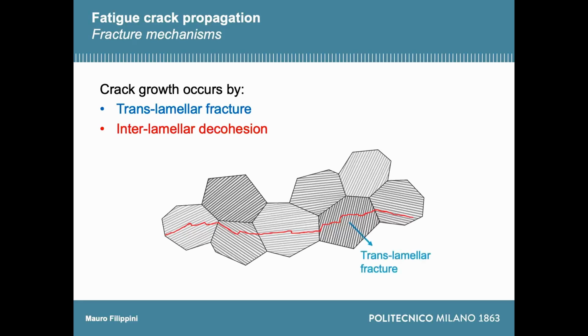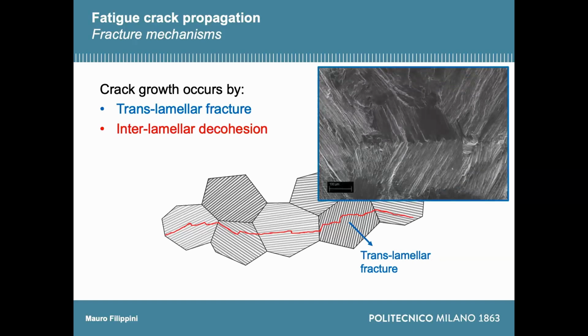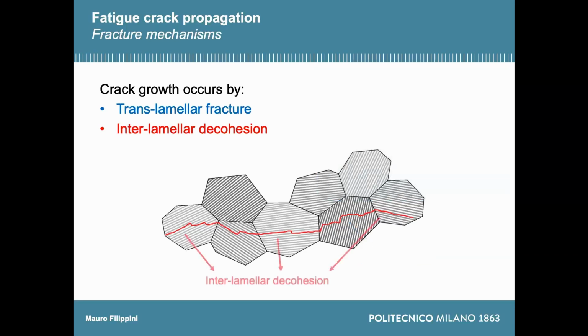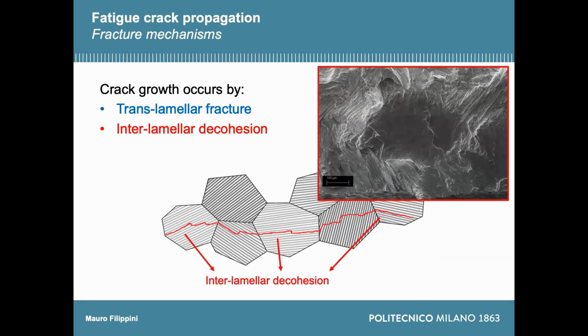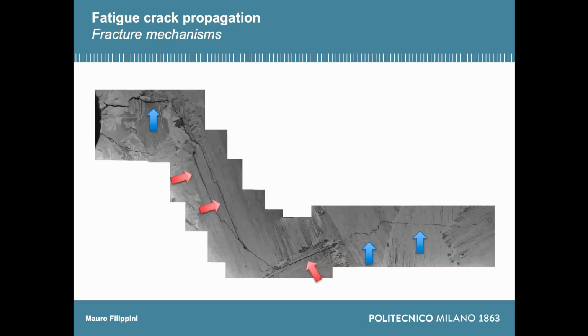So you do have the two mechanisms, the translamellar fracture and the interlamellar decohesion. So the translamellar fracture you can observe on the fracture surface by this kind of, let's say, images. Okay, and this is what is happening in interlamellar decohesion. So in this case, I would say that the material and the microstructure is the defect itself. Okay, so this is again the long history of this propagating crack through the microstructure.